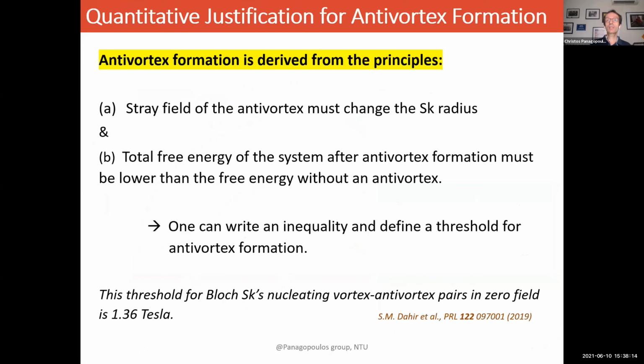So what is the quantitative justification for anti-vortex formation due to the presence of magnetic skyrmions in the heterostructure? Anti-vortex formation is derived from the following principles. First, the stray field of the anti-vortex must change the skyrmion radius. And the total free energy of your system after the formation of anti-vortices must be lower than the free energy without an anti-vortex present. Therefore, one can write an inequality and define a threshold for anti-vortex formation. And this is precisely what Eremin's group in Germany did in this article by Dahir et al. They calculated the threshold for Bloch skyrmions, and I will come back to this, nucleating vortex-anti-vortex pairs in zero field to be 1.36 Tesla.